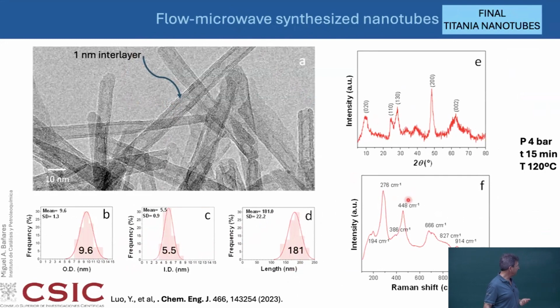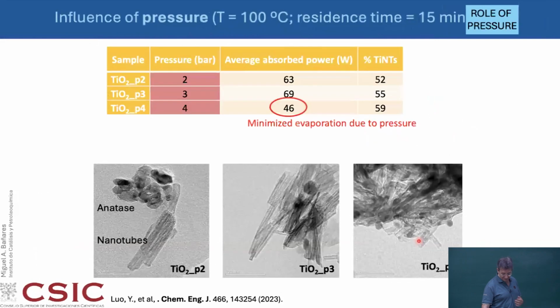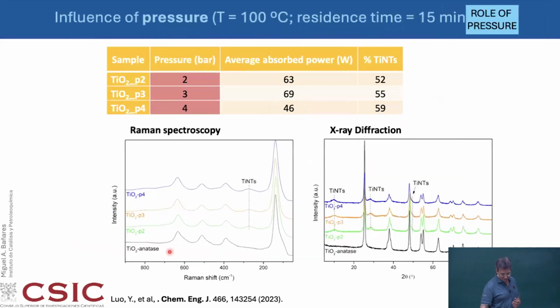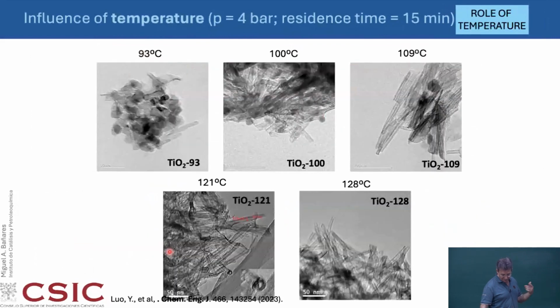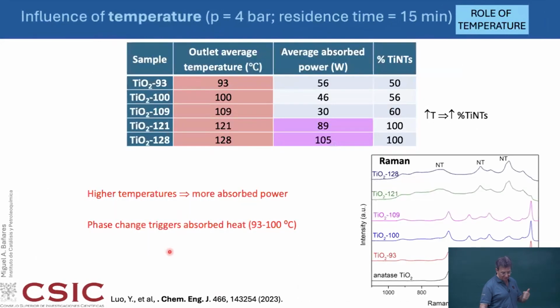Of course, Raman spectroscopy is always there. We can look at the different materials that we have on the precursor and on the product. So here you have basically the titanium nanotube Raman bands. And the nice thing of this system is that because you are going from this material into the tube... And okay, these are different controls, but the key message is not about this, but the possibilities, because when you have the sodium titanate and you wash away the sodium, it will scroll into the tube.